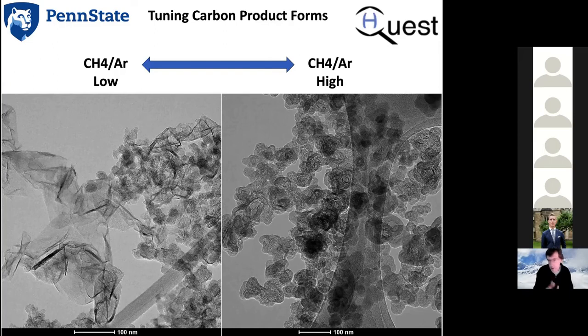So I mentioned the design of experiments. I'll only show you for the time here just a couple snapshots of results in terms of the methane to argon ratio, for a low methane-argon versus a high methane-argon ratio, in terms of the differentiation of either reactor conditions or fundamental conditions for the products produced under those 2 ratios. Under a low ratio, there's preferential production of a mixture of nanographene, which you're seeing here, along with a graphitic carbon black analog, again, the internal structure being the differentiator for why we call it graphitic, versus under a high methane to argon ratio, where there's in fact a relative absence